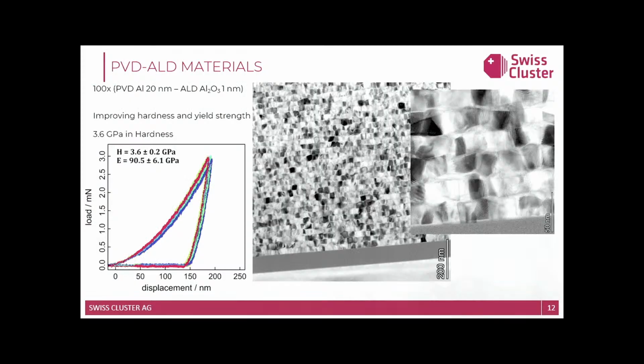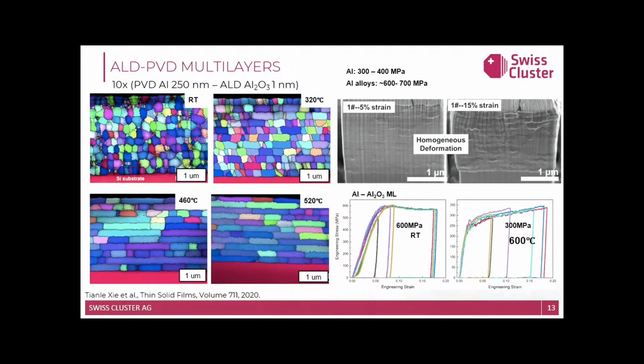So when we do mechanical testing for this type of microstructure, we see that it has 6 times the hardness of just pure aluminum, so 2 times harder than the strongest aluminum alloy. So this type of combination of material can increase the mechanical performance of the coating of just pure aluminum.